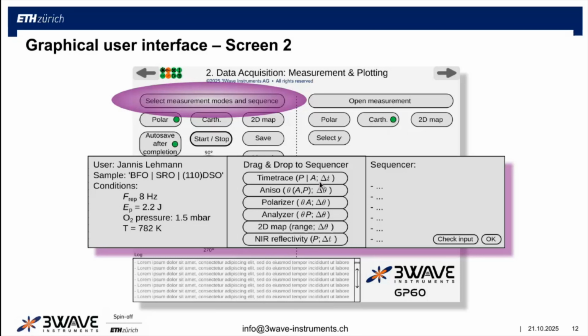And then we have a set of predefined scripts that you might want to use for your measurement. One very obvious one would be the time trace. You can drag and drop the time trace to the sequencer. You can define the polarization and analyzer position. Polarizer means the polarization of your infrared incoming light, and analyzer means the analyzed polarization of the converted green light. And you can set the step size for your measurement.